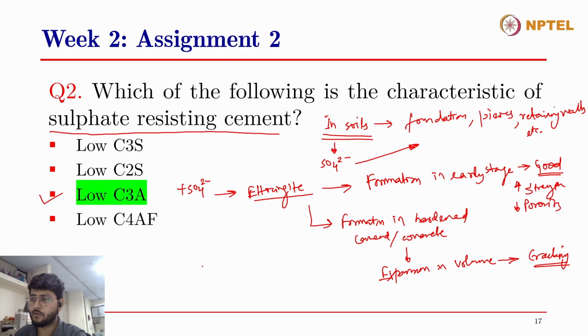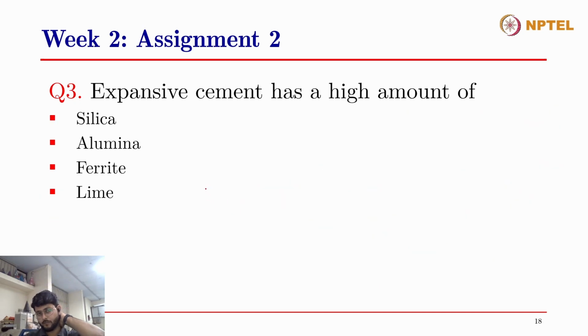So when we want to construct structural elements which are prone to sulfate attack or located in areas with high sulfate concentration, we want the aluminate content in those cements to be low, so that whatever aluminates are present will react at the early stage of hydration, and there won't be any further aluminates in the hardened state to react with the sulfates, even if there is a sulfate attack at a later stage. All right, so this is the idea behind low aluminate content in sulfate resistant cement.